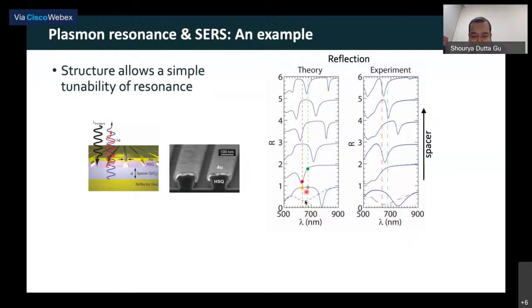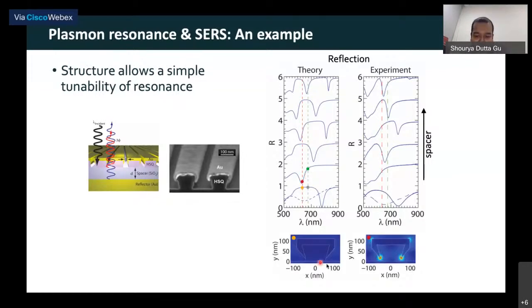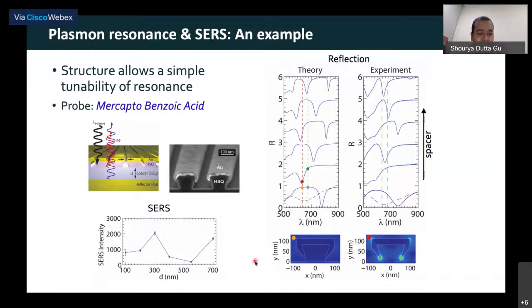So if I take this particular value of D, I see that the structure is non-resonant, that there's no resonance at this particular wavelength. However, for this particular case where D is 150, I have a resonance at both the values or close to both the values. Now, if I compare the fields, comparing this particular case, I see that the field is very low. So it's all blue colored. However, for this case where it's resonant, I see that you have a lot of red regions, which we call the hotspot regions.